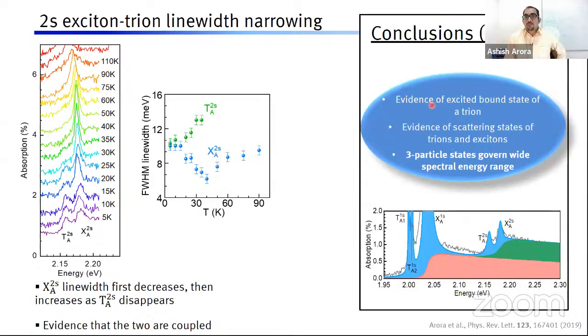Therefore, in conclusion, we have found an excited bound state of a trion here, and we also found evidence of scattering states of trions and excitons. We also find that these three particle states govern a wide spectral energy range. For example, we have these excited states of trions, and we also have this continuum of the trions, which runs throughout the spectrum, which was not seen earlier. For more details, you can refer to this work.